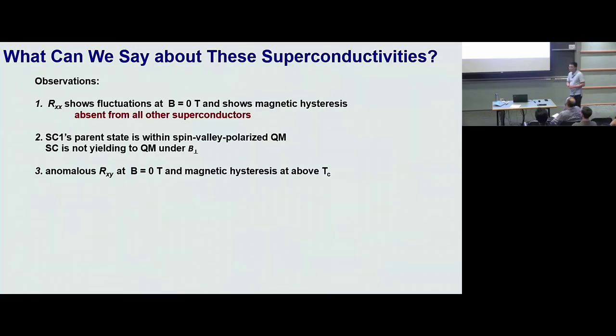Okay, to summarize, we have 3 observations. We have RXX fluctuation at zero magnetic field in the superconducting state, and we have magnetic hysteresis. This is absent from all previous superconductors. This tells you it's an orbital magnet. Second, SC1's parent state is within that spin and valley polarized quantum metal. And this boundary between superconductivity and the quantum metal is not tilted when you apply out-of-plane magnetic field. Okay? That's consistent with number 1.